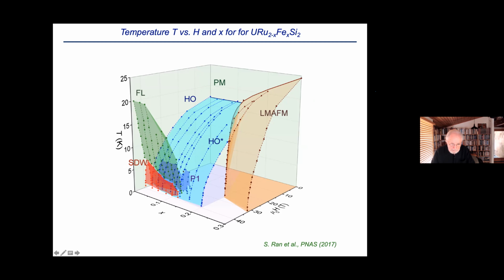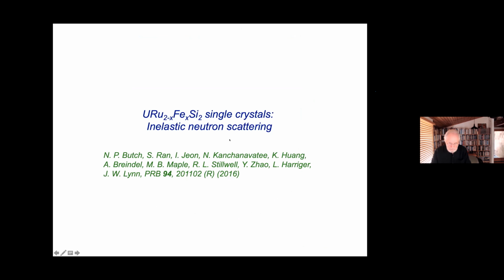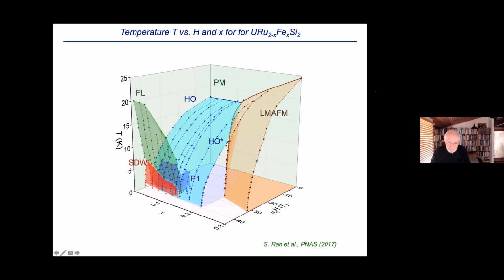restructuring of the Fermi surface, or that's what's believed. And then this is where it crosses over into a Fermi liquid on this side right here. And then over here, you see the large moment antiferromagnetism. And so it cuts off the hidden order in here, but then the hidden order reemerges as you go to higher fields like this, okay? So it's a very interesting and complex phase diagram showing the interrelation of all these different phases that are driven, in this case, by the substitution of iron, that's the iron composition, and the magnetic field in these high field studies.